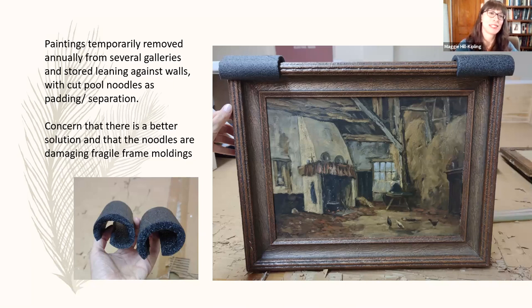This one was submitted from an institution that annually has an event where they have to remove all of their art from the walls in several galleries. And currently their method for storing these is using these pool noodles, which are ethafoam, which are actually a pretty great material because these are probably commercially available ones. They may have some other materials in them that might not be ideal, but it's actually a really cool idea. The concern that the person who submitted it had was that the pool noodles might not be as effective for that separation as possible, but also that they had some frames that were really ornate and that might be being damaged by them. And that concern is really quite accurate.